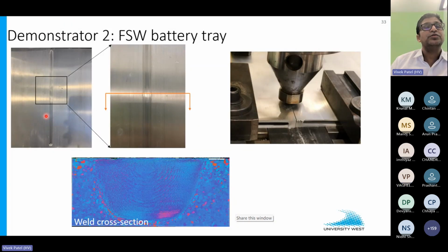So how it looks, you see that the butt joint surface is almost like extrusion lines on the plate. And if you see the cross sections, again you see there is no shoulder deformation on the top. So your weld nugget is completely probe dominated or probe driven. And also you see the significant onion bands as a typical friction stir welding microstructure.